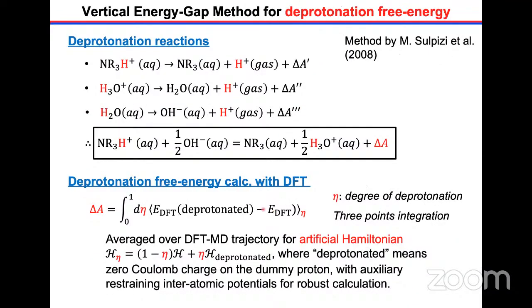So we can calculate this kind of free energies using the method of Sulpizi et al. about 10 years ago. Then we have the half reaction, something like this. Then calculate this free energy independently, and then combining together, we get the total free energy of the protonation, deprotonation reactions in water. Then we can calculate using DFT by using the thermodynamic integration method. Eta corresponds to a degree of deprotonation. Then we have performed this kind of simulation using DFT molecular dynamics simulation of an artificial Hamiltonian depending on the eta. And here deprotonated means zero Coulomb energy of the dummy proton. Then we can get this kind of delta.